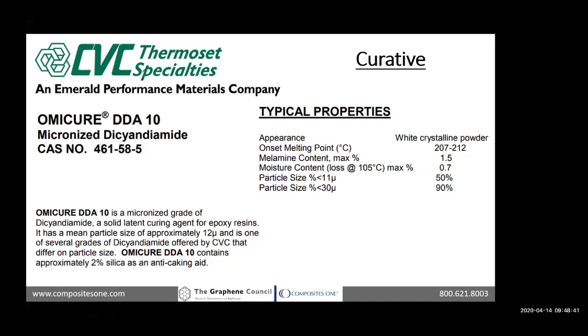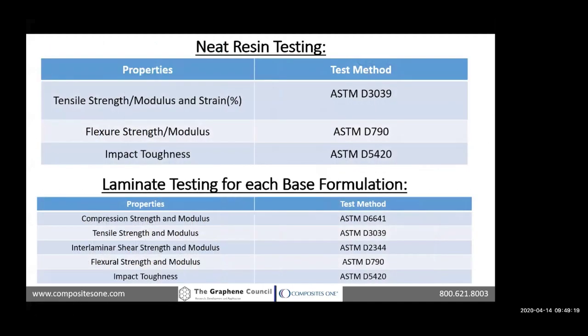So for the broadest application that will allow for prediction of results to higher performance systems, we've decided on a DICY curative. This type of curative has broad applications, including everything from general layup processing to adhesive formulations. The DICY also allows us to have a lot of control over blending at an elevated temperature. So when we combine this hardener and BIS-F, we'll have already blended in the graphene that you send us in an elevated temperature environment, and DICY allows us to blend in that curative without having a very fast cure time. We can control the cure process as we elevate the temperature. So those are the systems we're going to use.